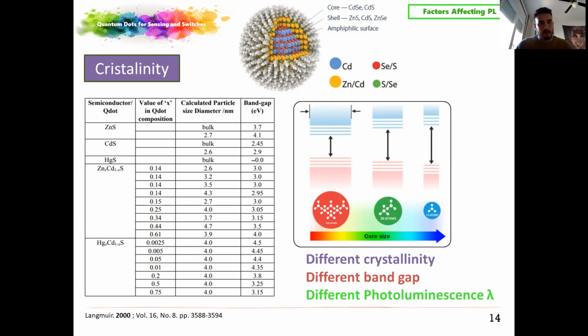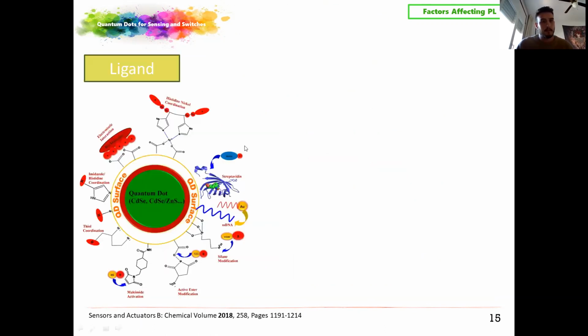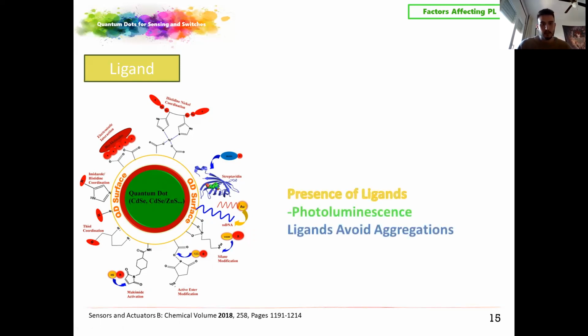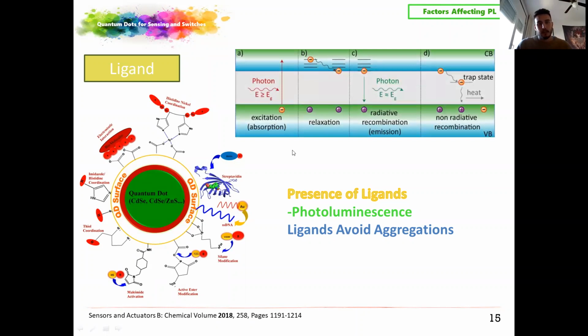So to finish, the last main property to be controlled is the ligand. Ligand is probably one of the most important, along with the size, because they avoid aggregations. But they can also reduce the photoluminescence depending on the type of ligands or the bonding between the ligand and the quantum dots, because normally ligands interact as a hole trapping.